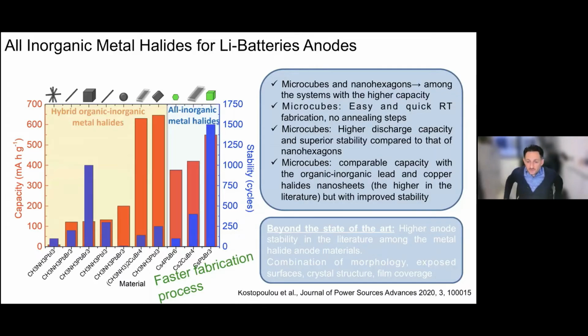This is how this approach compares with other perovskite structures. Most of the structures used in the past are hybrid organic and inorganic metal halides. Our approach is based only on all-inorganic metal halides, and you can see that our results are very close to the performance of the hybrid organic and inorganic metal halides as far as capacity is concerned. But the stability in our case, especially for the three-dimensional structure, is much better in terms of cycles compared to the hybrid organic inorganic halides.